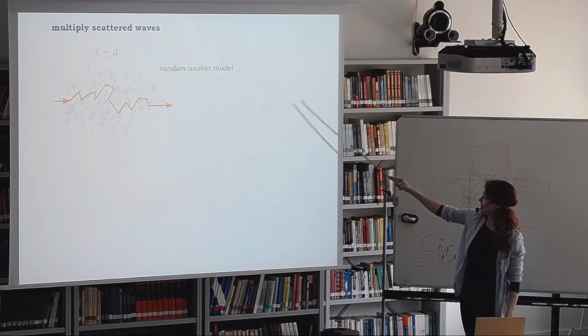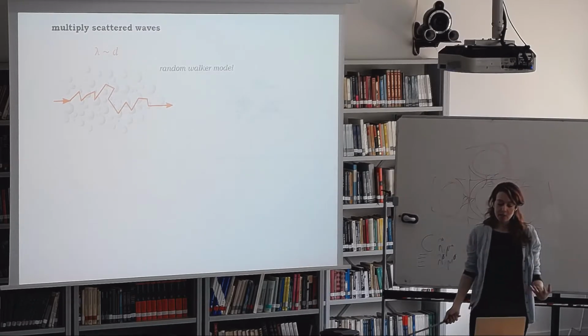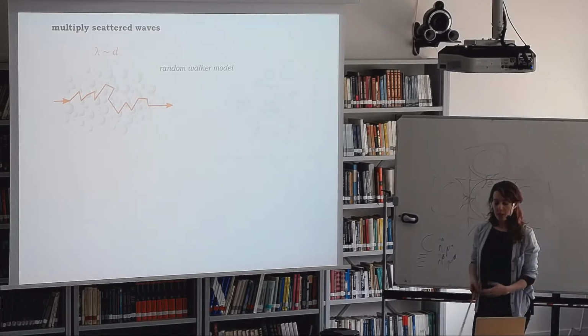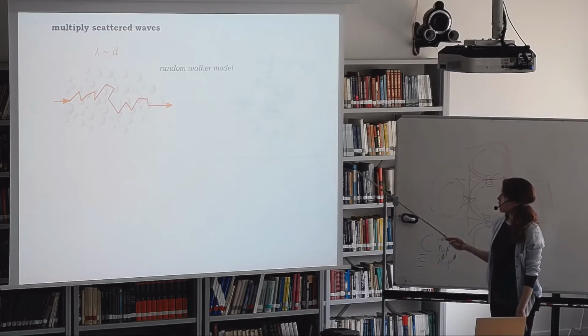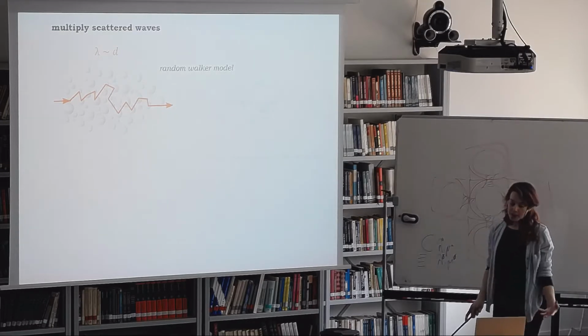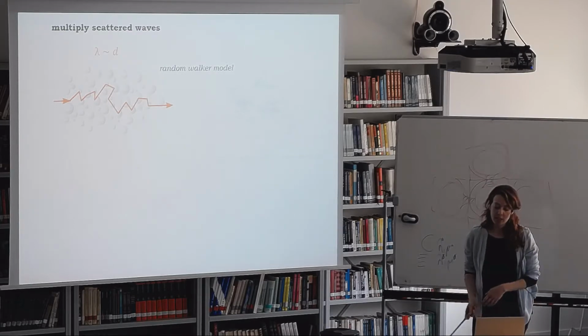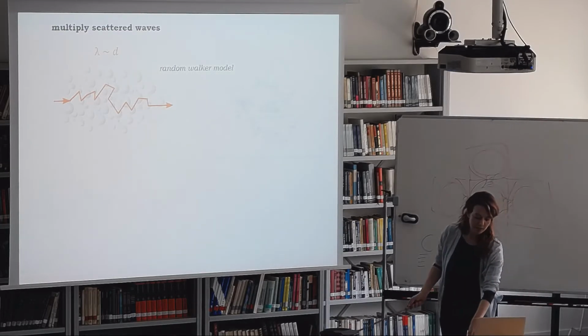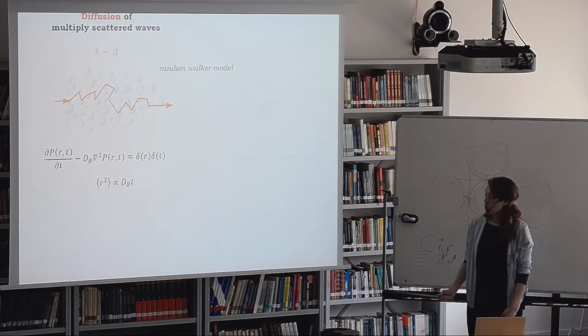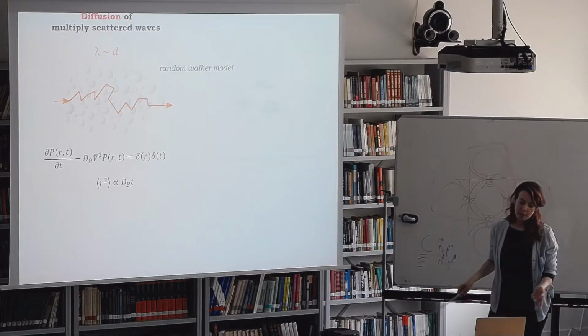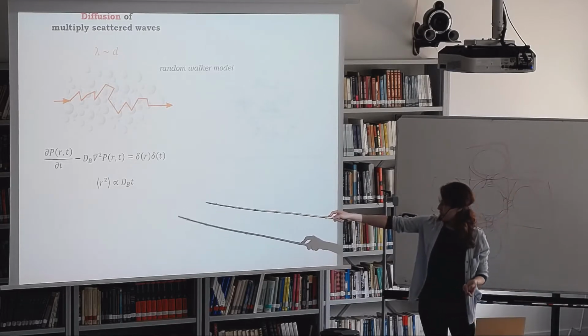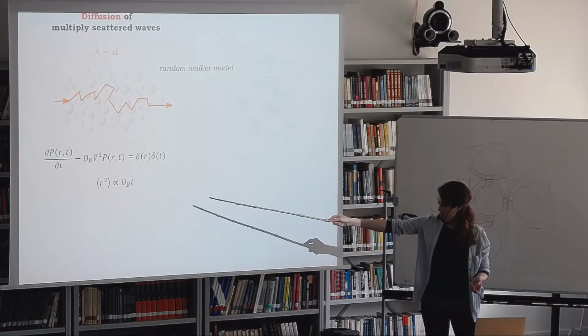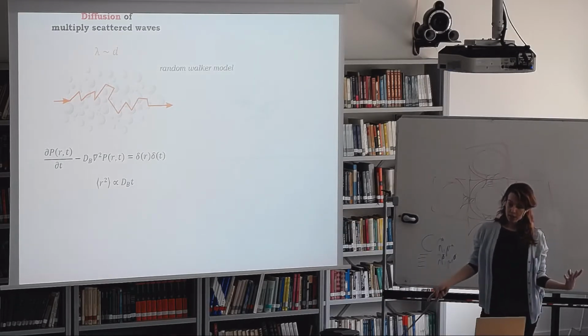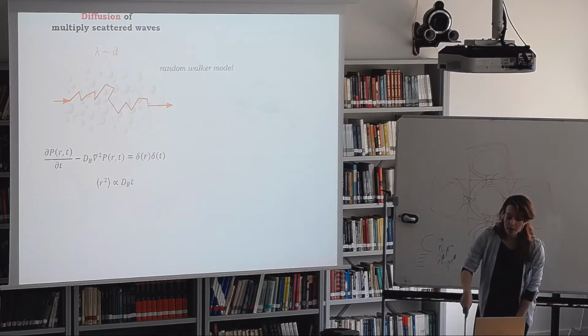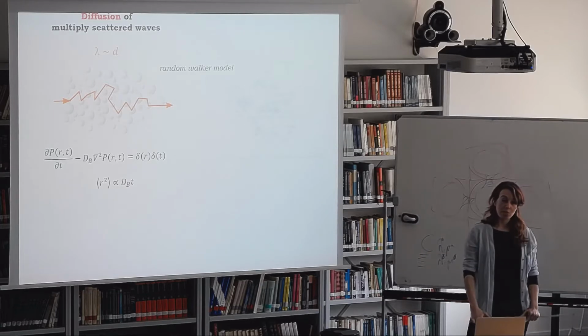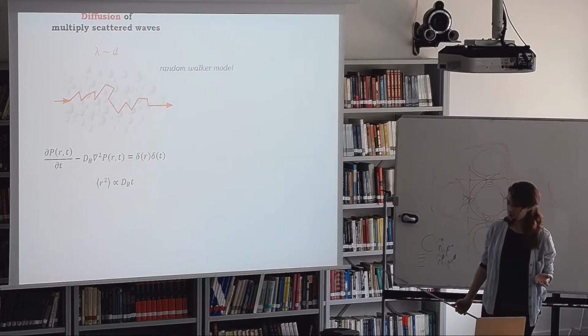Can you kind of see this? It's a little GIF of a random walker. So this is the same model that has been used to describe, for example, the random Brownian motion of particles. We can't predict exactly where the walker will end up, but we can estimate statistical quantities such as how far on average he can spread out. To do this, we use a transport equation such as the diffusion equation. This one says that the mean squared displacement is proportional to time, so it increases with time at a rate that's governed by the diffusion coefficient, D. This is the same type of diffusion equation that is used, for example, for heat transport in a solid.